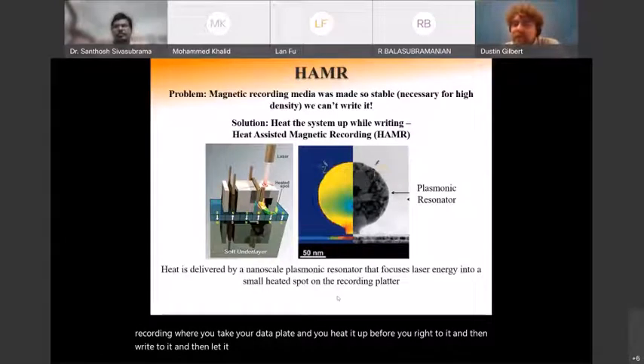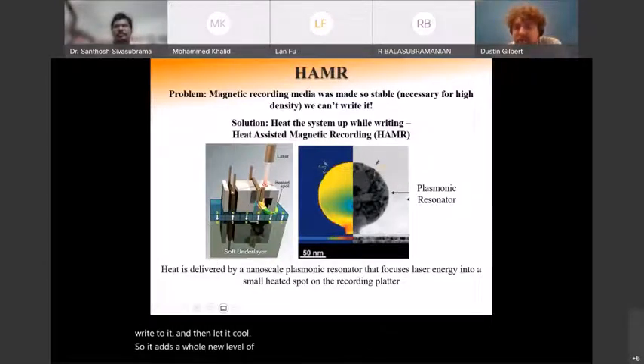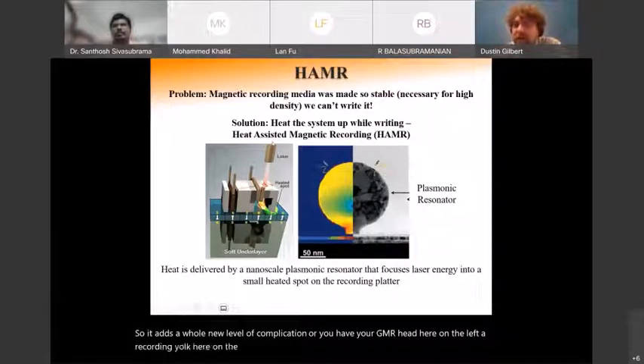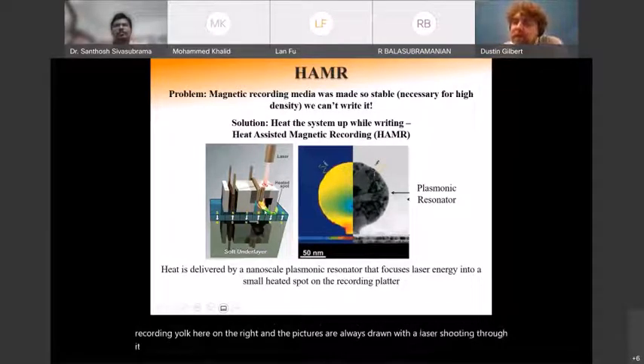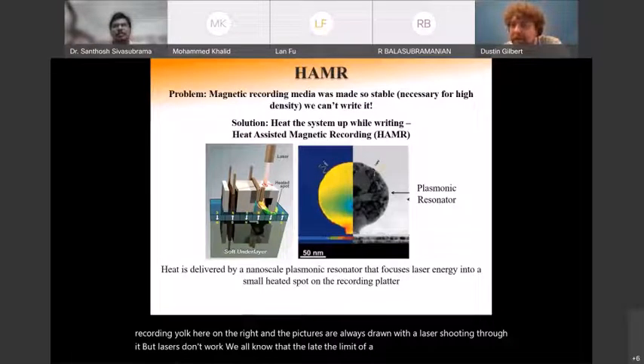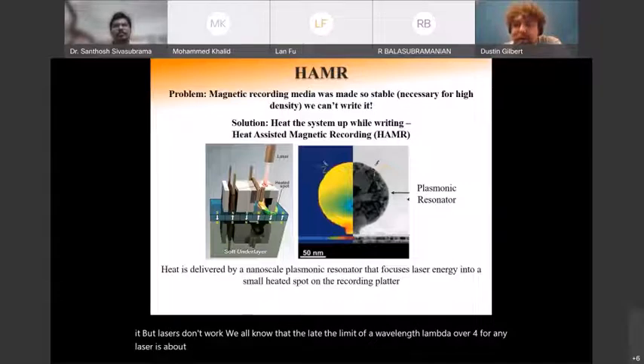So it adds a whole new level of complication, where you have your GMR head here on the left, a recording yoke here on the right, and the pictures are always drawn with a laser shooting through it, but lasers don't work. We all know that the limit of a wavelength, lambda over 4 for any laser, is about the limit of your resolution. You hit diffraction after that. And so in order to write a data bit, which tends to be on the order of 20 or 30 nanometers in size, you can't do that.